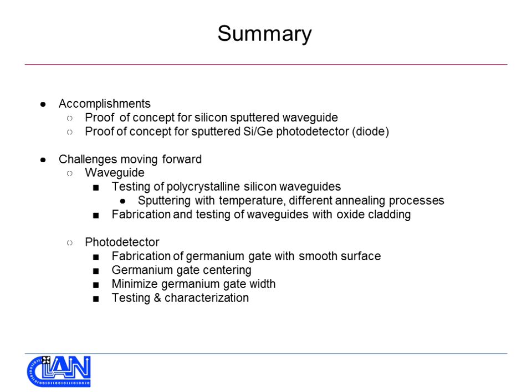So in summary, our accomplishments overall are a proof of concept for silicon sputtered waveguide and a proof of concept for sputtered silicon and germanium photodetector, which is in the diode form. And the challenges moving forward for the waveguide are testing of polycrystalline silicon waveguides, sputtered with temperature and using different annealing processes, and the fabrication and testing of waveguides with oxide cladding. For the photodetector, we'd like to fabricate germanium gate with a smooth surface, center the germanium gate with more accuracy, minimize the germanium gate width, and of course define or redefine our testing and characterization procedures.